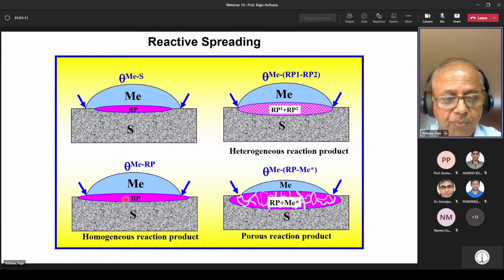You also have systems where the reaction product grows faster than the liquid spreading. And in this case, liquid spreads on a modified surface. The reaction layer may not be just a single homogeneous reaction product. You can have multiple reaction products. And you can also have situations where the reaction product layer is porous, mainly because of volumetric expansion or due to some sort of cracking, which would cause the liquid volume to change.